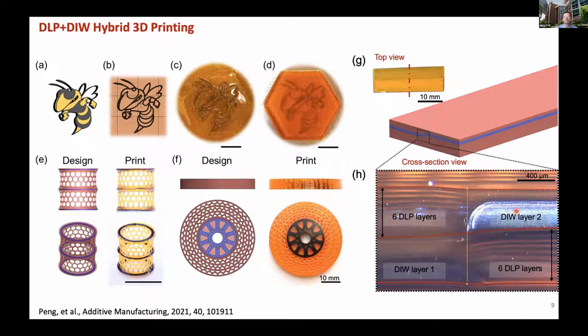For DIW, the nozzle we're using is typically about 100 to 200 micron, so each layer is about 200 microns thick. That is incompatible with DLP print. So normally we put about 6 to 8 layers of DLP, then we can print one DIW layer. But you can see the transition is actually pretty smooth because we're using the top-down approach. After you print the DIW, you sink your printed structure into the resin reservoir, so the resin refills and covers it. So you can see here, we have one DIW layer here, and the other one here. You can see a relatively smooth transition here. But certainly, the software needs to calculate how many layers of DIW we print and how many DLP layers. We need to do those kinds of calculations.